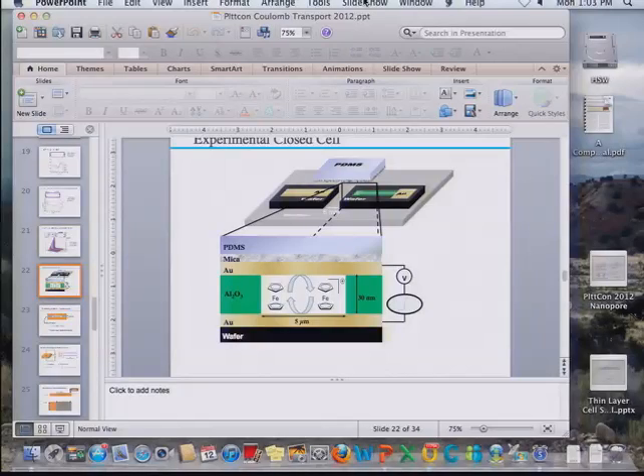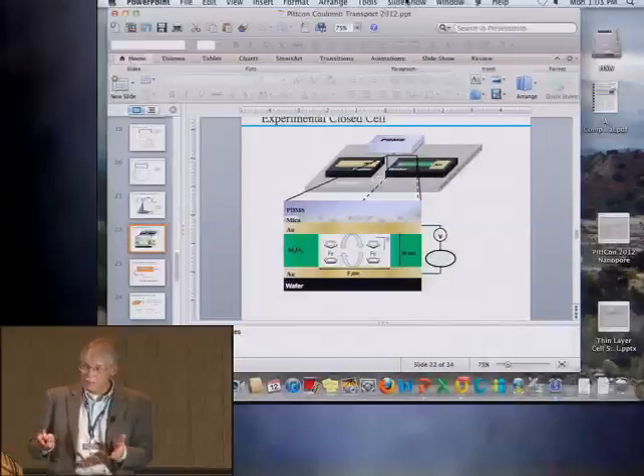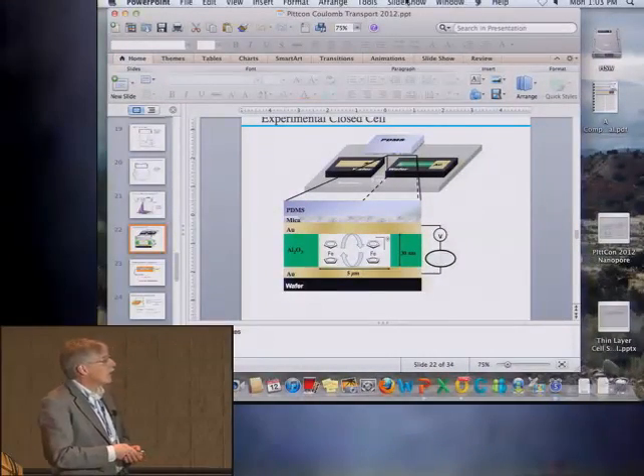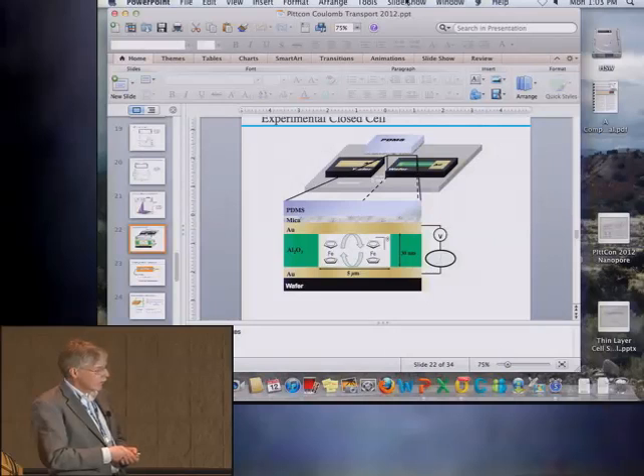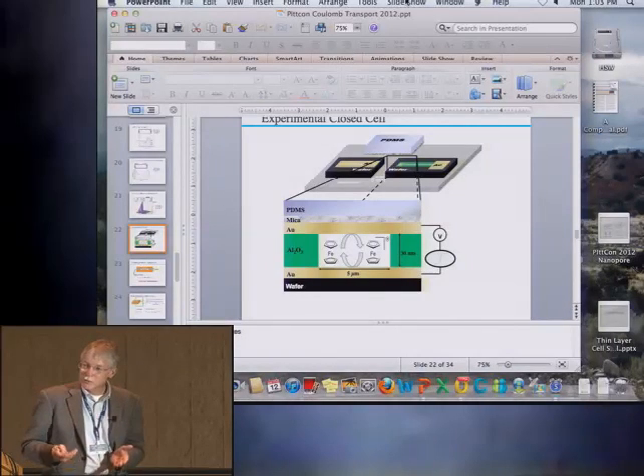All right, so we've been trying to build these cells. This is a very hard problem. Two gold electrodes separated by, say, 30 or 50 nanometers of solution. We use aluminum oxide as the walls of the beaker here, and aluminum oxide is deposited by atomic layer deposition. And then we've had a hard time figuring out how to make a closed cell, put the solution in a closed cell. That's the bugaboo of all of this research.